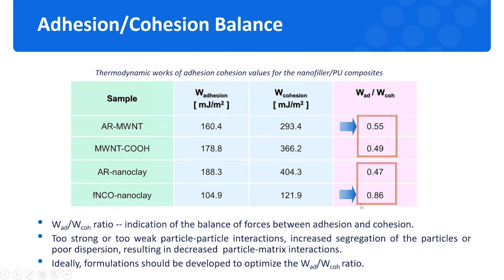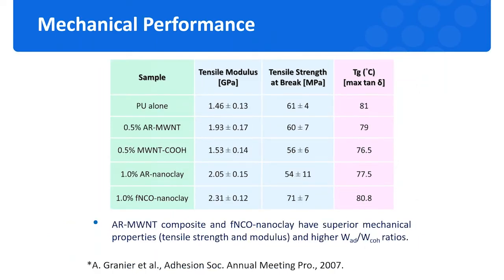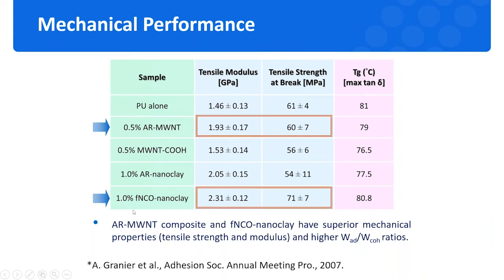So the better the ratio, the better the affinity between the nanofiller and the polymer matrix, so we predict that those two samples have the best affinity with the polymer matrix and give a better quality in the final composite material. So these are our predictions before we make the final product. And here we measure the mechanical performance of the final product to prove our prediction. So here we have the non-treated nanotube sample, and also the treated nanoclay sample with the better tensile strength and other mechanical performance. That's saying those two fillers are the best choice for the polymer matrix. So this just shows the evidence that the work of adhesion to cohesion ratio is a very good indicator to predict those kinds of formulations with the help of the IGC technique.